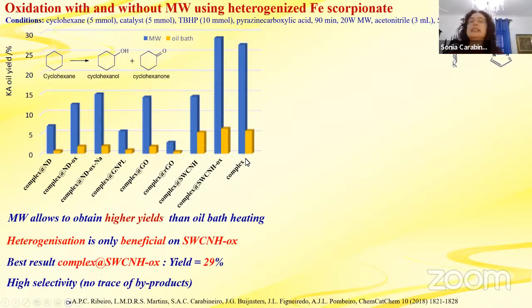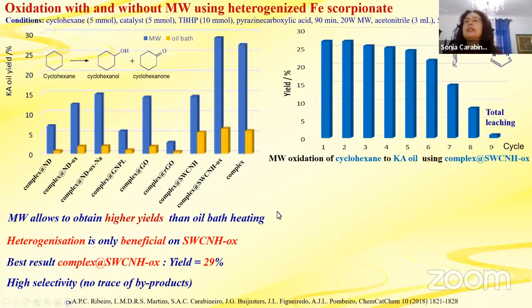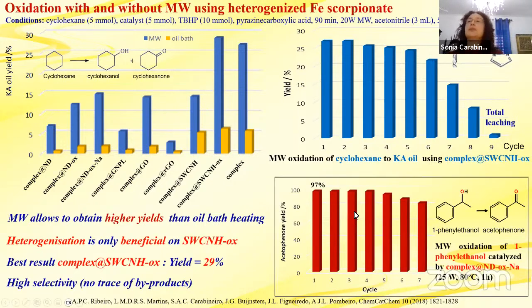And again, in all cases, high selectivity, no trace of byproducts. And if we see here the recycling, we see that there is a decrease in activity, and after 9 cycles there is a total leaching. Too bad. We also tested not just the oxidation of cyclohexane, but of 1-phenylethanol to produce acetophenone, and we